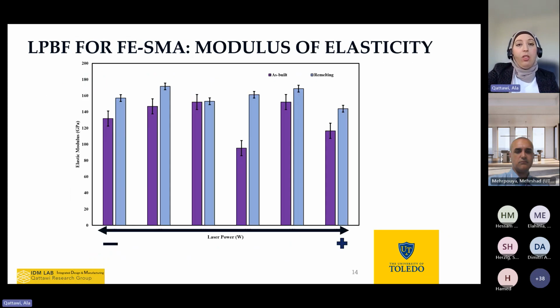As a regular alloying system that will have high loading, we looked at the modulus of elasticity. And in this technique, we also applied a manufacturing technique called remelting. Remelting is basically the same as processing the material, but instead of the laser passing one time, we do it a second time. The remelting does not necessarily use the same laser power and speed as the initial scan, but it serves two purposes.